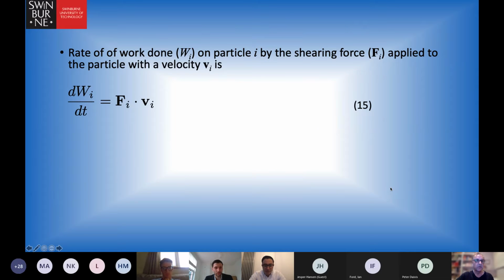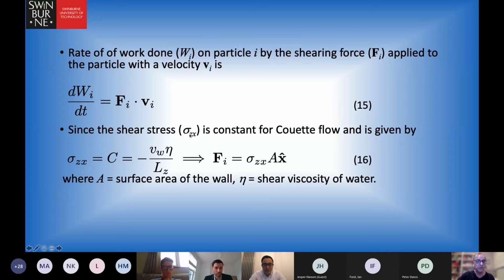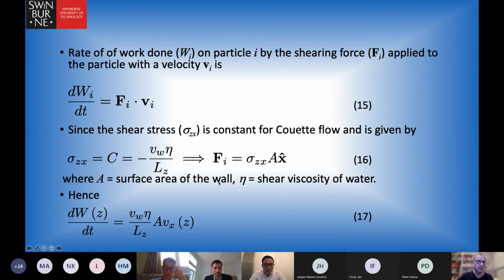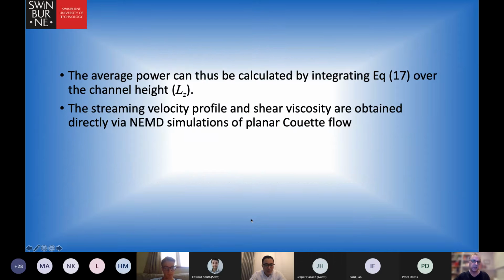What about Couette flow? That's quite straightforward. If you look at the rate of work on particle I by the shearing force applied to the particle velocity VI, it's just this simple expression 15. Since we know that for Couette flow the shear stress is a constant and is given by this expression here, where eta is the shear viscosity and VW is the velocity of the wall, we get a simple expression for the force, which we can substitute into equation 15, and then we get our expression for the energy dissipation at position Z within the channel. To get the total power, we just integrate over the whole channel height, and then we can get the total power for Couette flow.